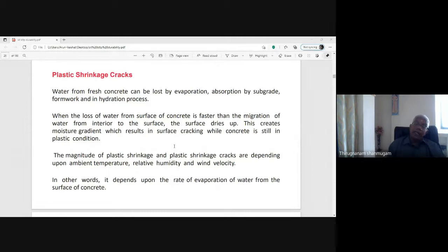Otherwise, if you start the concrete process, that is the roof slab concrete, in the morning at 9 or 10 a.m., then at the end of the concrete placement, at about 12 noon or 2 or 3 p.m., the temperature is very high, about 40 or 45 degrees. So the evaporation of water from the surface of the concrete is more and more. It causes shrinkage stresses. So it is best practice to arrest the rate of evaporation by suitably adjusting the placing of the concrete.